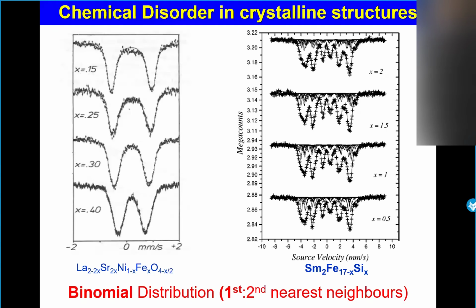So now, probably you have studied some systems where you introduce some substitution to make the system much more simple. And of course, it's possible to do Mössbauer. So, for example, in this case with lanthanum, strontium, nickel, iron, oxygen, you can see the lines are broadened. If the lines are broadened, that means you have different environments, of course, because you are mixing iron, nickel, and maybe the strontium and lanthanum influence.